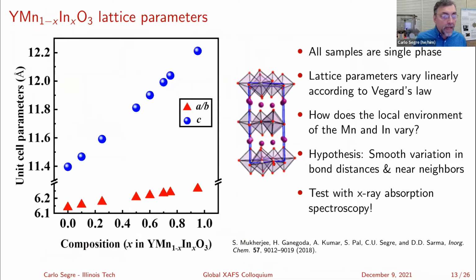And if you plot the lattice parameters, and this is our data now, you see that the C parameter increases as you put indium in. Indium's bigger, so it smoothly gets bigger. It follows a nice linear trend, as do the A and B parameters. They also get larger, but more slowly. And you can see the lattice parameter at the start here for the pure manganese is 11.4, and the A and B parameters are 6.15 or so. So all the samples are single phase. The lattice parameters vary according to Vegard's law. And the real question is how the local indium and manganese environments vary.